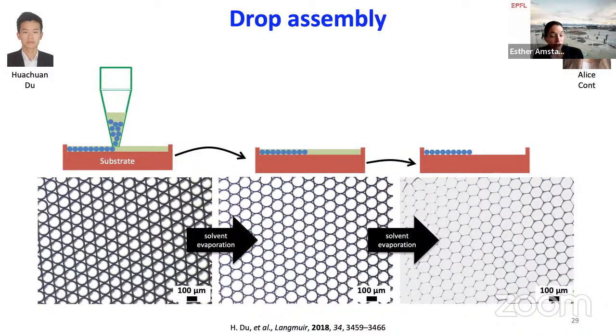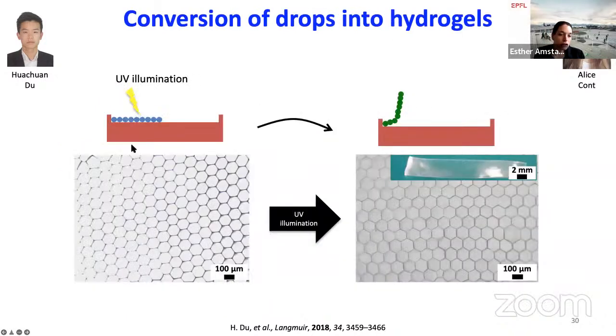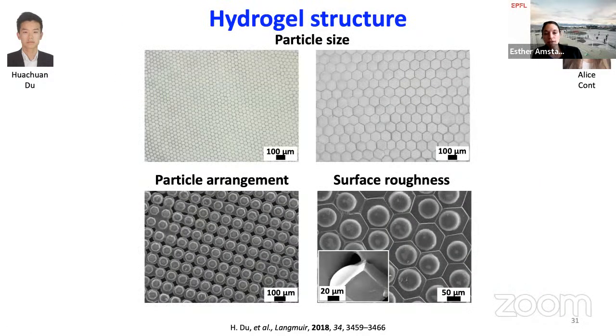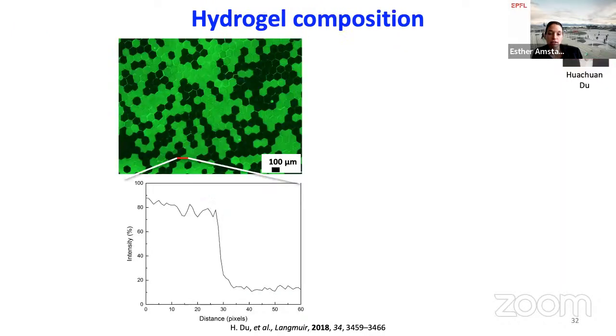And only at this point, we started to initiate the polymerization reaction, with the result that the polymerization reaction was not completed when almost all the oil was evaporated, such that basically these interparticle connections were lost. And so we used the rest of unreacted monomers to covalently connect these adjacent particles, and what we got is integral microgels, which had very well-defined micrometer-sized patterns. So we could tune the microstructure by tuning drop size and the arrangement, and we could tune the surface roughness by controlling the polymerization kinetics of these monomers.